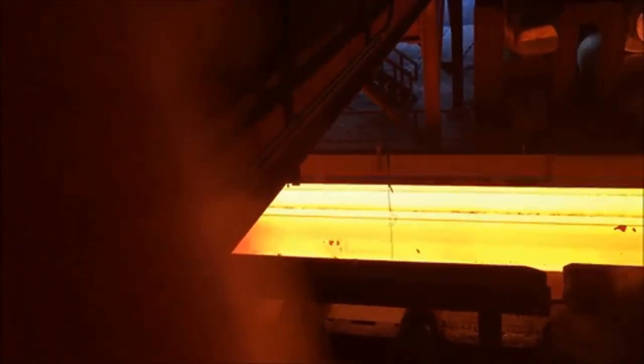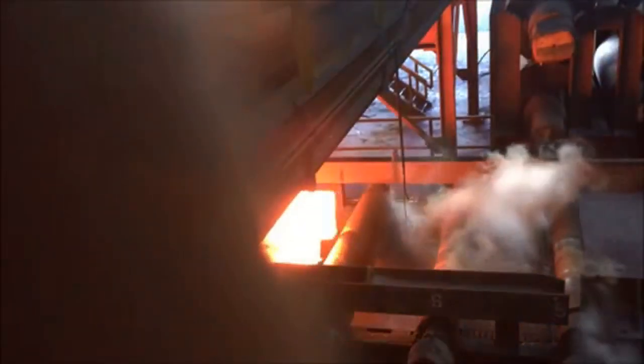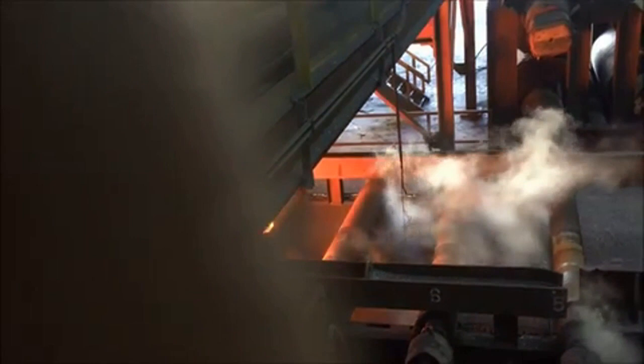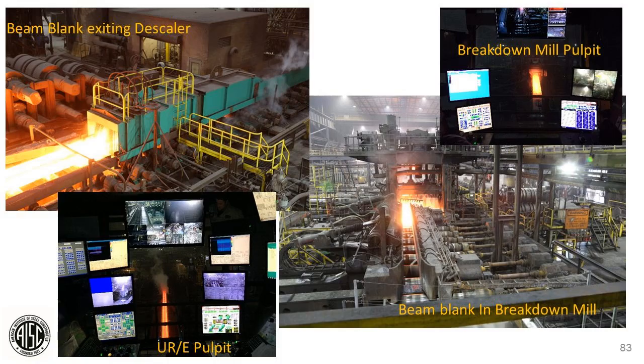So this next step that this beam blank is going to go through will be the breakdown mill that we talked about earlier. Next slide, please. Here's where we left off with the beam blank exiting the descaler, and this larger picture on the right-hand side is the breakdown mill, and you can see the manipulators guiding the beam blank. That's because a typical breakdown mill can have different portions of the roll doing different work. So once this beam blank exits the other side, it would possibly be brought over to another portion of the roll. Maybe these manipulators move over to the right, for example, and using a different portion of the roll would do different work.